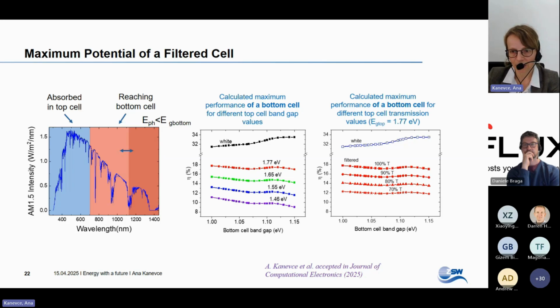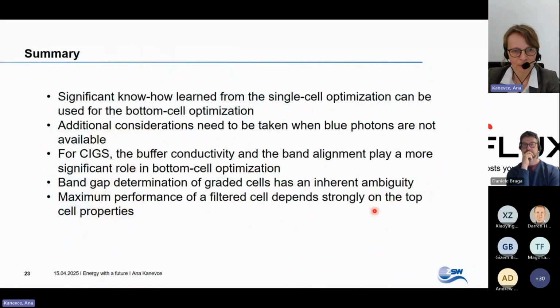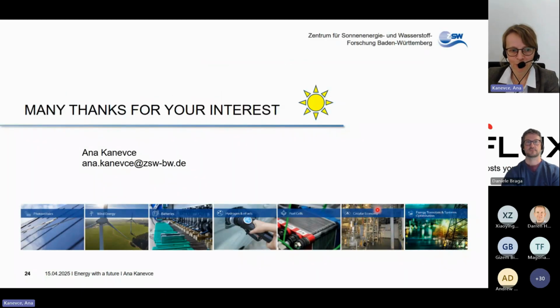And now to summarize, a lot of the know-how learned from single cell optimization can be used for a bottom cell. One has to take additional consideration when blue photons are not available. One of them is that the buffer conductivity has to be really high, and band alignment plays an even more significant role. The band gap determination of graded cells has inherent ambiguity, so one has to keep that in mind. And maximum performance of a filter cell depends strongly on the top cell properties. So the bottom cell is somehow playing a supporting role in this structure. So one has to keep that in mind. And so with that, I thank you for your interest and for your patience and for listening and for inviting me.